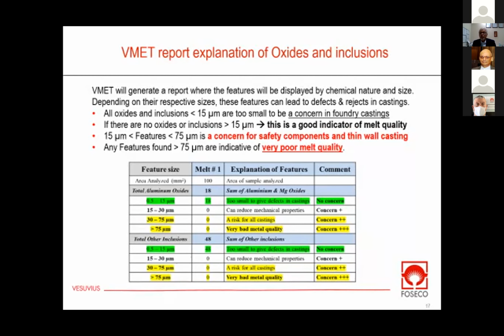This is in certain castings. This is when we start having castings that break, castings where we have cracks, castings that are not gas proof, not pressure tight, because there was some oxide or some porosity in the casting. So this tool is a very interesting tool to try to map and benchmark the melt before we actually make the casting.